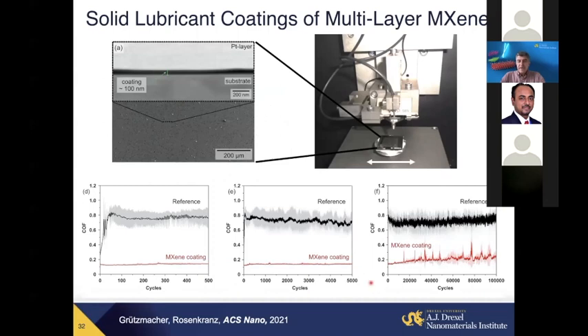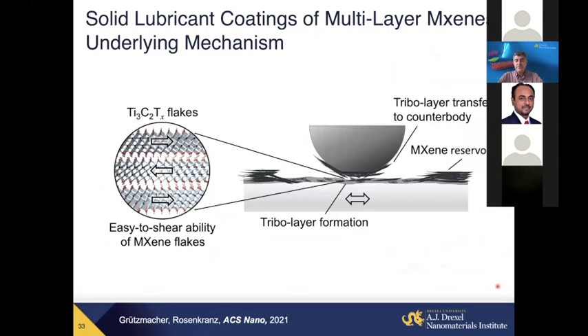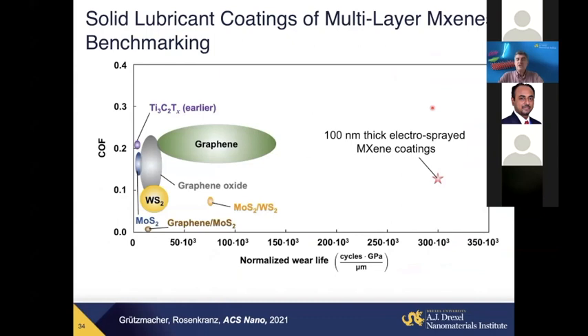And actually, it cycled well over a long period of time. You can see 100,000 cycles. There are some spikes appearing, probably coating starting to wear off, but it still works here. So it means that it's possible to get a very significant improvement in the friction coefficient here. And the reason is potentially because MXene flakes cover basically the surface of the materials. They cover the surface of the counter body, making this tribo layer transfer, and they shear it here.